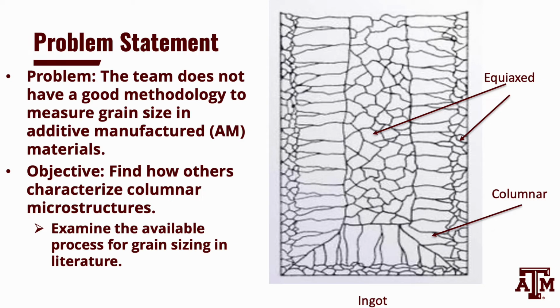This is an example of a casting. This is representing an ingot, a mass of metal that has been cast into a size and shape. When this structure is solidifying, the heat is moving from the inside out. At the very edge, we can see an equiax grain structure. Moving in from the edge of the mold, we start to see the grain structure change from equiax to columnar. The thermal gradient of the ingot and mold is what defines the size and shape of the grains. In this work, I will be researching ways to find a new methodology that is suited for columnar grains in AM materials.